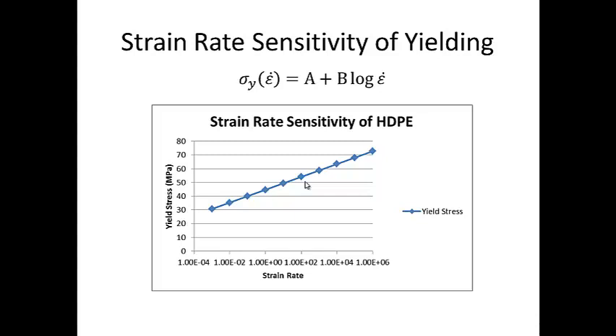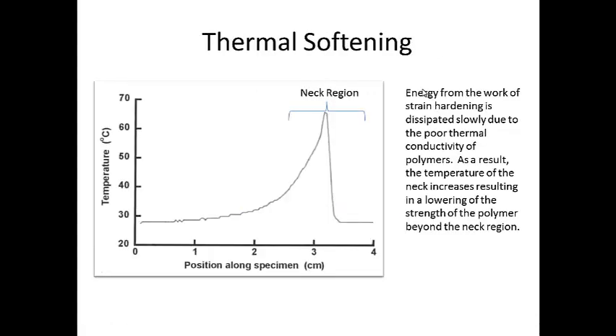Now keep in mind that the yield strength of the point at which necking will occur is highly dependent on the strain rate of the load that you're applying to the material. So if you apply a very slow rate of strain, you get a low yield stress, and if you apply a high rate of strain, you get a high yield stress. So what this means is that the yield strength as a function of strain rate is equal to a straight line equation when we take the log of the strain rate. In order to solve this equation, we'd have to be given the material parameters A and B in order to do the solving.